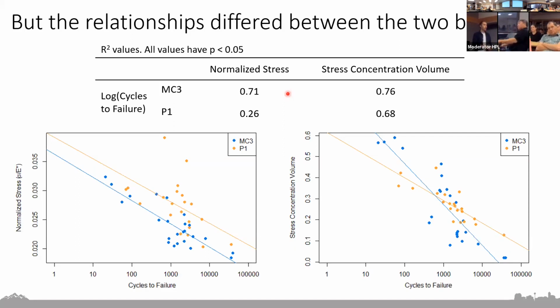concentration volume were almost equally predictive of fatigue life in the third metacarpal bone. But in the proximal phalanx, we see they're quite different. Stress concentration volume was a noticeably better predictor of fatigue life for the proximal phalanx bone. So then we tried to investigate a little bit more why we were seeing these different relationships between the bones.